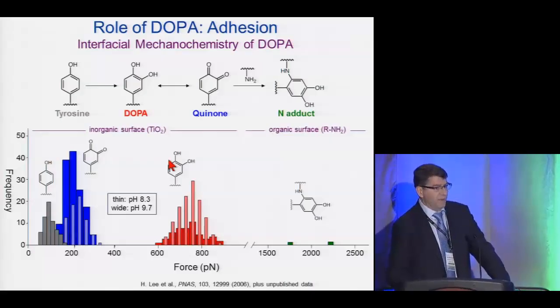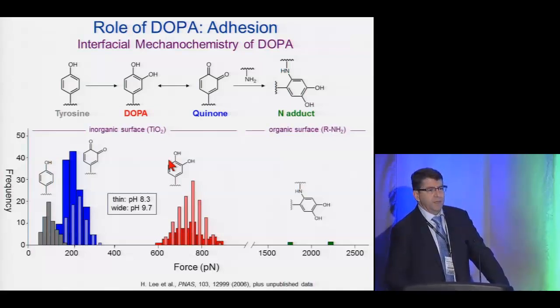Now, these numbers sound very small, and they are small. But if you're familiar with force landscapes of chemical bonds, you would know that down here near the origin, below 10 piconewtons, is the force necessary to rupture a hydrogen bond. Most receptor-ligand interactions in biological systems, like avidin, biotin, integrin with its ECM ligand, rupture in this area here. So this type of interaction in the 600 to 800 piconewton range for a single amino acid on an inorganic surface is truly an exceptional adhesion bond.